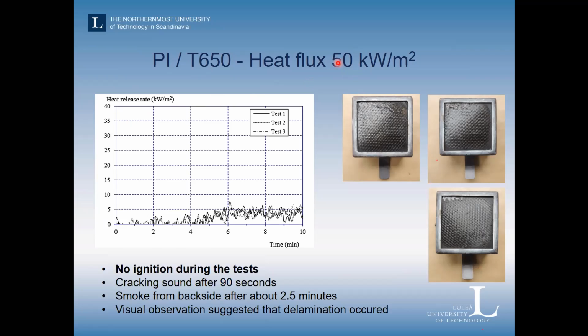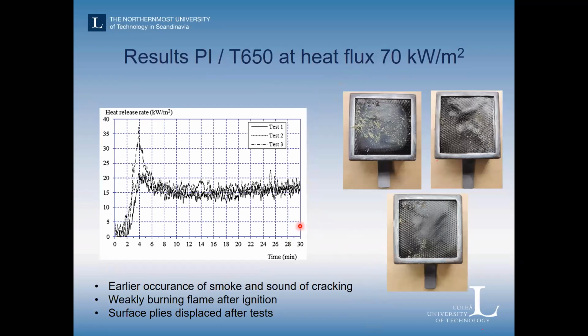The heat flux is 50 kilowatts per square meter. During the first 10 minutes, there is no heat release. There is no ignition during the test, and there's no measurable heat released, but it delaminated the composite. Increasing the heat flux to 70 kilowatts per square meter, it took around 4 minutes for something to happen, and then it happens.